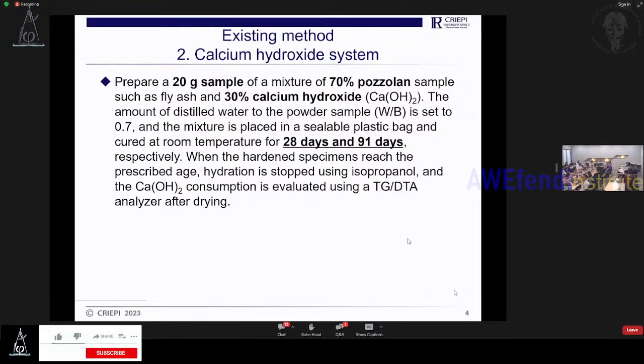The second one uses calcium hydroxide. We mixed 20 grams of the samples, in which 70% is pozzolan like fly ash and the other 30% is calcium hydroxide. We need to cure the paste specimens for about 28 days and 91 days. After that, we determine the consumption amount of calcium hydroxide by TG-DTA.